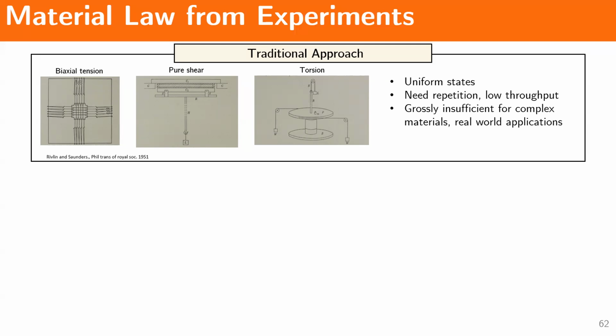So what people have done traditionally, and this is what Rivlin and Saunders did back in the 50s to model their rubber materials, is they impose a state of uniform strain in the material. They do these very careful experiments to get a state of uniform strain. And by measuring these boundary forces, you can get the stress associated with that strain. So one experiment basically gives you one stress and strain data point. This is rather low throughput because you have to repeat these experiments multiple times.